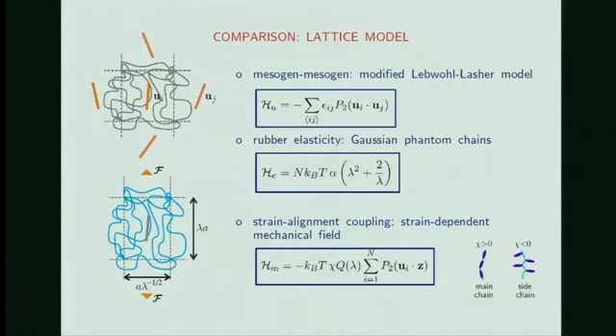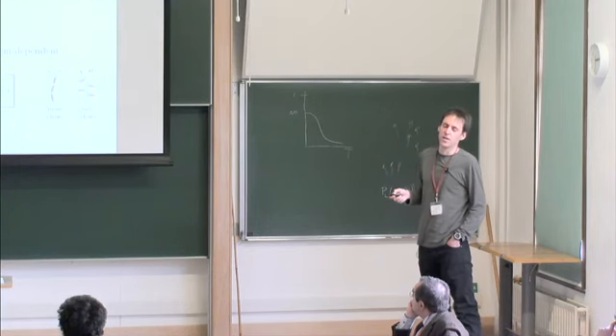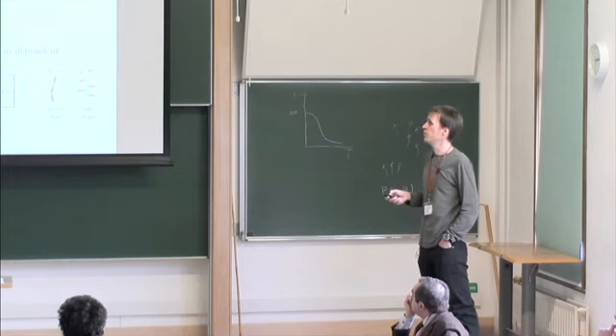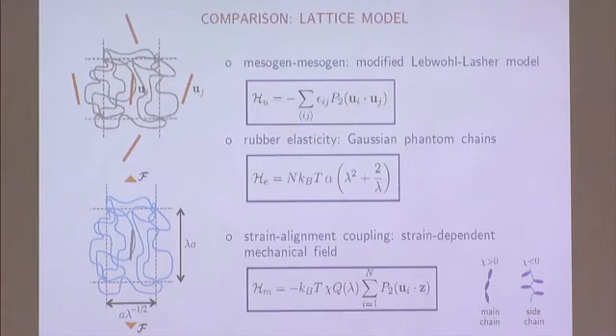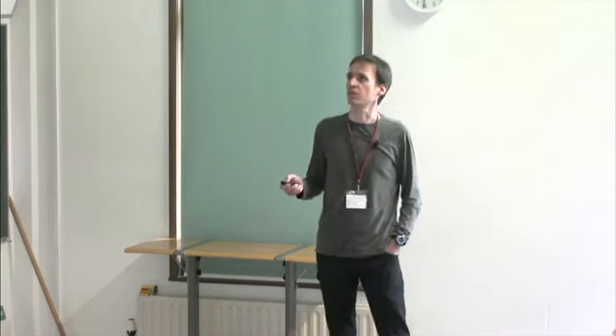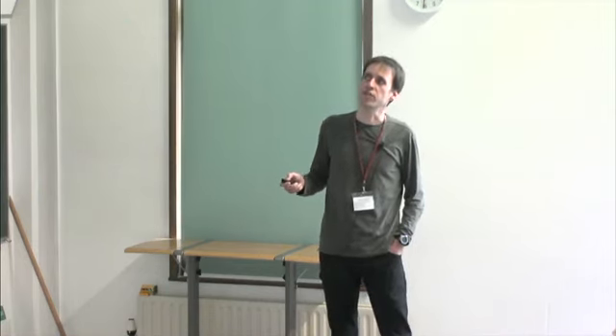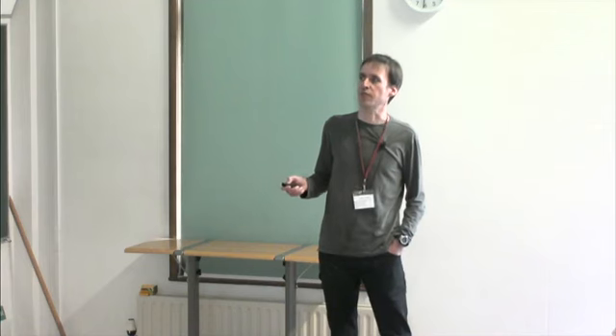For epsilon ij positive, you end up with a parallel aligning tendency, and this is what's frequently used also in normal monomeric liquid crystals to model various types of systems. Of course, thinking of an elastomer, one needs to introduce deformation somehow. So we simply thought of a deformable cubic lattice as shown in this plot, and if we assume that we have so-called phantom chains, non-interacting Gaussian chains, a pseudo-Hamiltonian of this kind can be written down. So lambda is this distortion factor, and here we also assumed sample incompressibility.